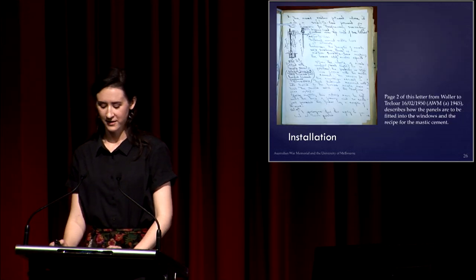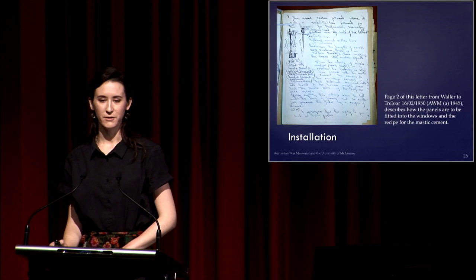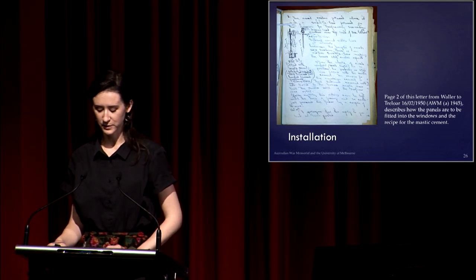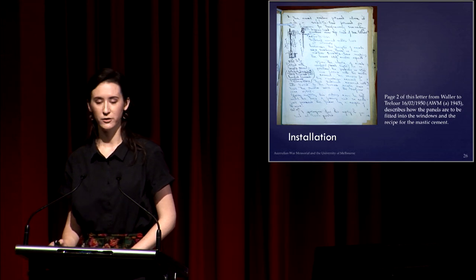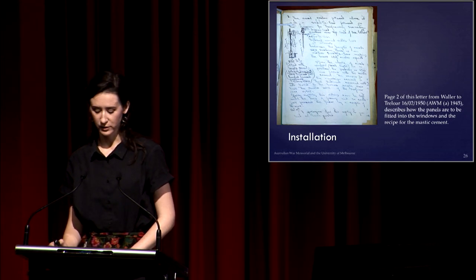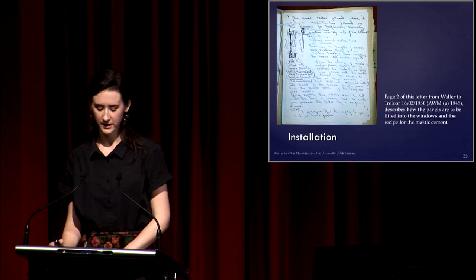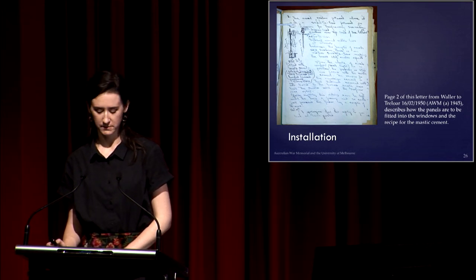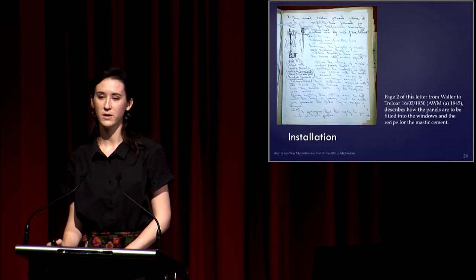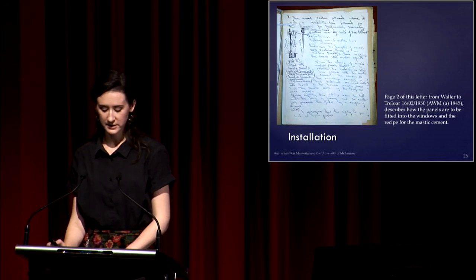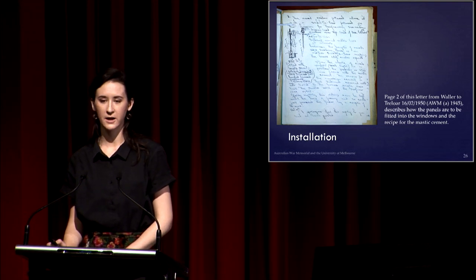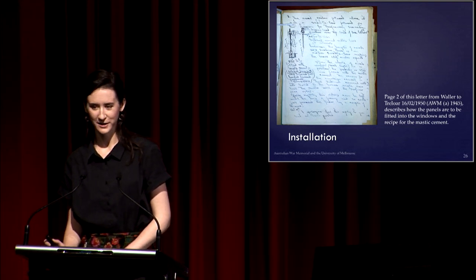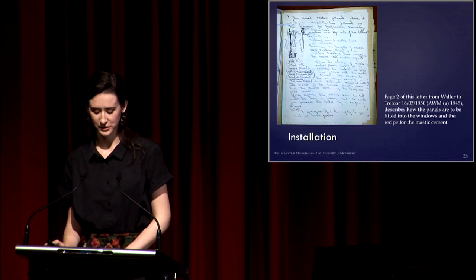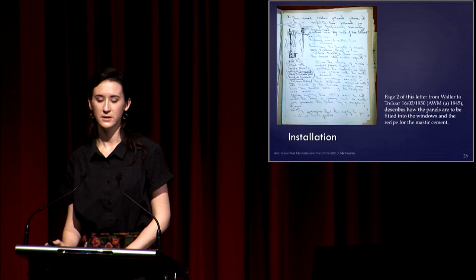The installation of the windows was done in a matter of days. Brass angle irons were set into interior masonry and coated with a mixture of copal varnish and linseed oil for good adhesion with the mastic cement. The glazed panels were then inset from the bottom up in situ, using additional panel joining leads and mastic to set them in place, as specified in this letter from Waller from 1950. Mild steel saddle bars were then secured to the brass angle irons, specifically every 26 centimetres on the interior to reinforce the structure, and then tied to the panel joining leads using copper wire.